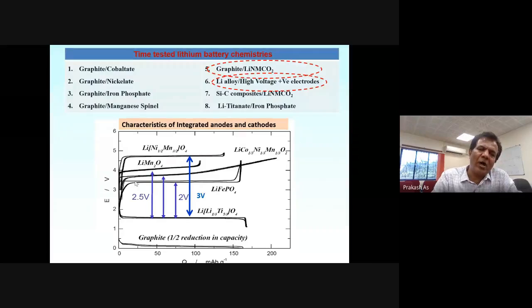If you see here, these are called half-cell reactions. Half-cell reaction means, for example, you take this compound, a lithium nickel manganese oxide spinel. When you make a cell versus lithium metal, you have a plateau like that. So you have a potential of about 4.6 volt, and the graphite intercalation potential is close to about 0.1, 0.2 volt, right? Graphite capacity is about 375 milliampere hour. Just for comparison, to see it in one graph, I divided by half to reduce the capacity. So here the potential of graphite is here. If you make a battery with graphite in combination with lithium nickel manganese spinel, then you see a voltage of about 4.5 volt, right?